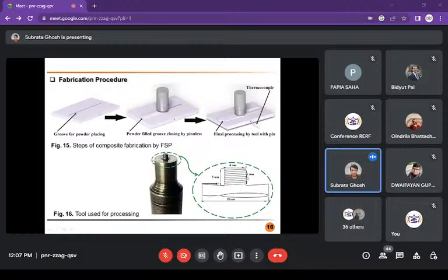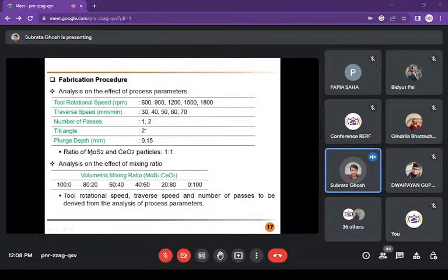So this is a typical shape of tool shown here. One of my scholars did it like that. He used this pin, which is a little cylindrical and threaded. The geometry is also shown here. Here I have chosen a few parameters like tool rotational speed, traverse speed, number of passes, 1 and 2, tilt angle, and plunge depth, meaning how deep the pin is inside, and the ratio of MoS2 to CeO2 that is varying. Initially it was 100-0, then 80-20, 60-40, 40-60, 20-80, and 0-100, in order to check the influence of these kinds of ceramic particles.